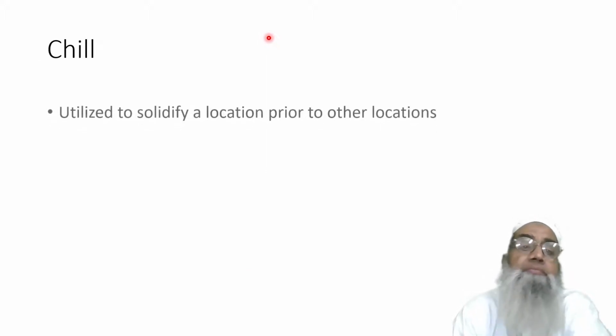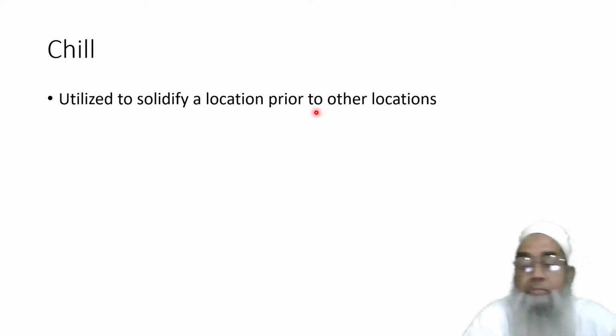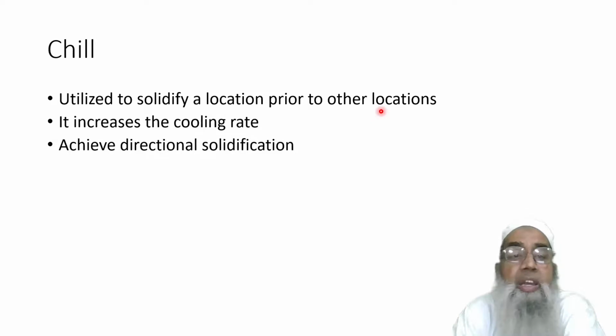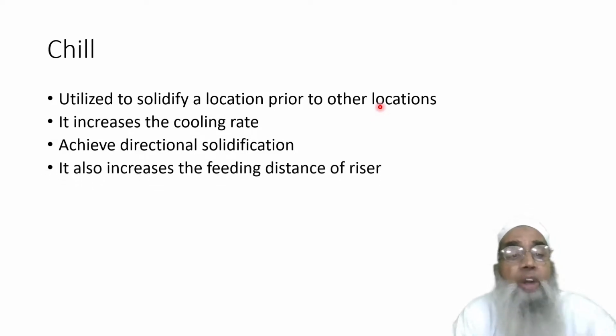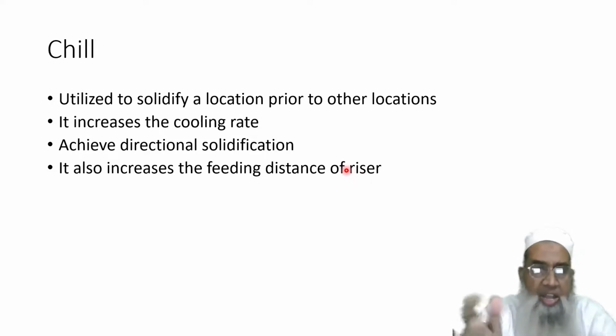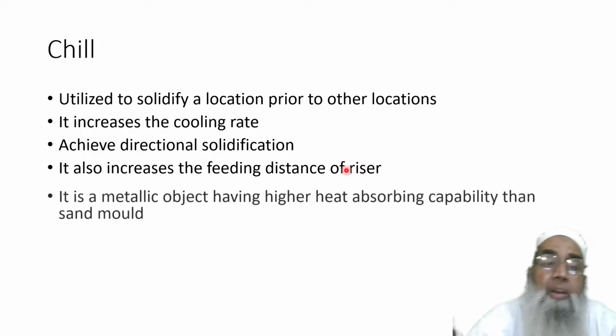Now, a chill. A chill is utilized to solidify a location prior to the other locations. Moreover, it increases the cooling rate, achieves directional solidification, and it also increases the feeding distance of the riser. By providing a chill, the feeding distance that we have seen can be enhanced.